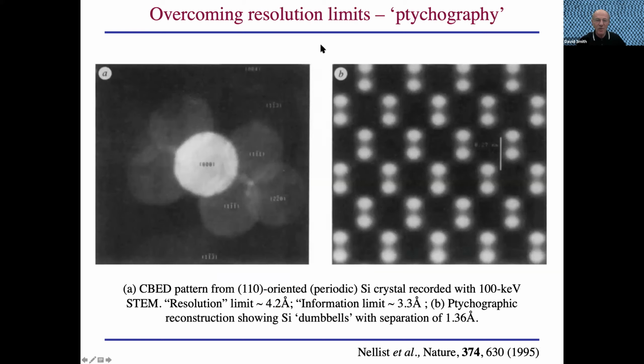Ptychography is the flavor of the recent microscopy community. Cowley and Rodenburg, and also Nellist and co., started doing some STEM observations back when, overlapping convergent beam diffraction pattern disks, and then reconstructing. Here is a very important example: resolution limit 4.2 angstroms, the information limit after taking into account the envelope functions about 3.3 angstroms. Okay, so 3.3 angstroms would be pushing that microscope, but they're able to resolve the silicon dumbbells with a spacing of 1.36.